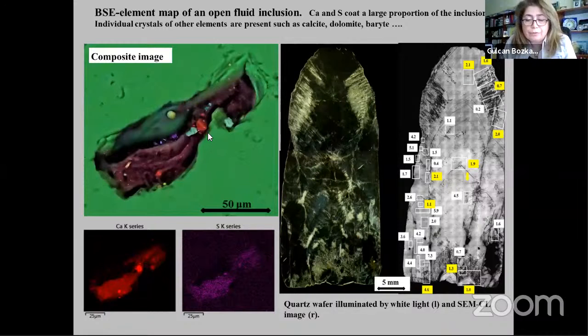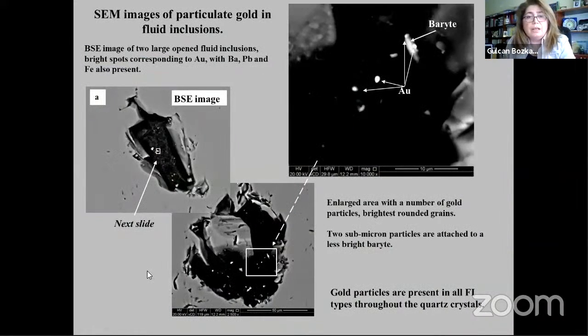The image on the left is the composite and individual element map of the large inclusions that contain numerous small solids. Here you can see the different colors represent different main elements. We see the coating in the fluid inclusions is dominated by calcium and sulfur. These are images of the large fluid inclusions that have been opened during polishing of the quartz wafer.